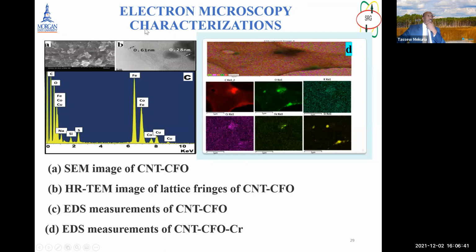And also we tried electron microscopy characterization. This is also one of the characterization mechanisms. As you can see, the SEM scanning electron microscope image of CNT CFO, and the HRTEM image, where we have lattice fringes and also EDS. And as you can see here on D, EDS gives by color and by element. As you can see by color, chromium is identified here. I don't know what this color looks like, it's like a gray, blue or something like that.